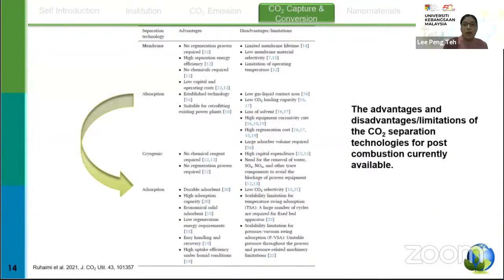To expand a little bit on this, as demonstrated, the comparison of different post-combustion CO2 separation techniques. So we know that the established technology is absorption. But adsorption appears to be a much better candidate for CO2 capture. It may be due to the fewer capture limitations, such as if you are using a durable adsorbent, we have a high adsorption capacity, then it will be more economical, low regeneration energy, easy handling and recovery, and also high uptake efficiency under humid conditions.